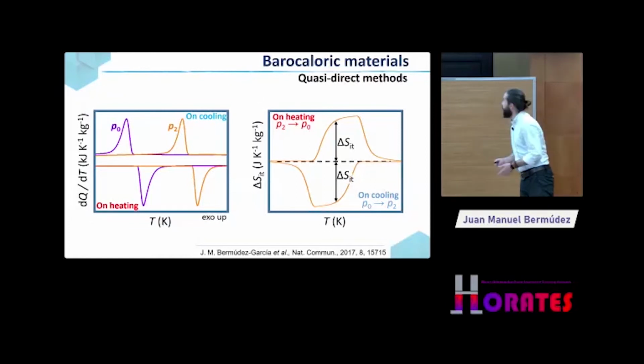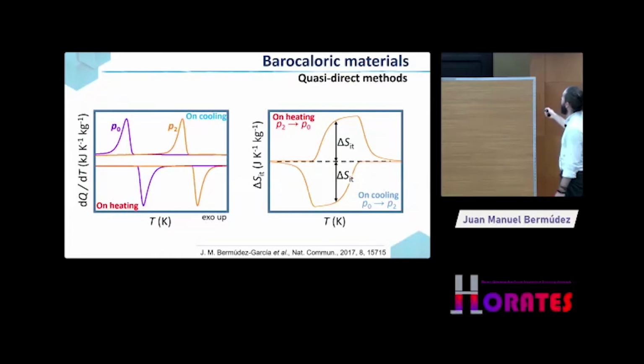So we do that as well for the heating part, and we have an inverse curve, very similar, which is shifted due to this thermal hysteresis, and you can obtain the barocaloric effect on cooling and on heating, because this process has to be reversible in order to use it as many times as you want. That's the reason you are doing the characterization on cooling and on heating, which is equivalent to pressurizing the material and depressurizing the material.